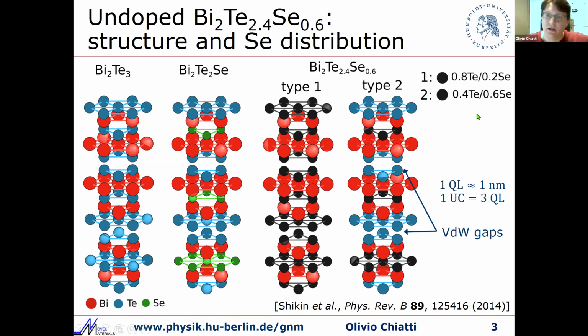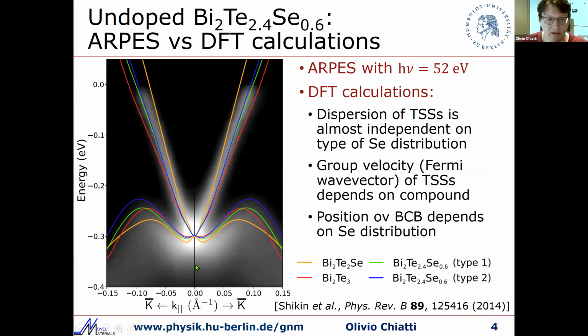The work looked at ARPES measurements and density functional theory calculations to see the effect of these distributions. And here in gray and black, we see the ARPES measurement, and we can see very nicely the topological surface states with nearly linear dispersion and the Dirac point down here. And the lines are the results of density functional theory calculations. The blue and the green lines are the two types of distributions of selenium, and it shows that the topological surface states are relatively insensitive to how the selenium is distributed in the crystal.